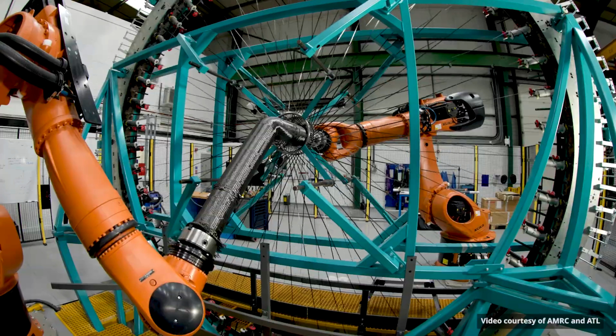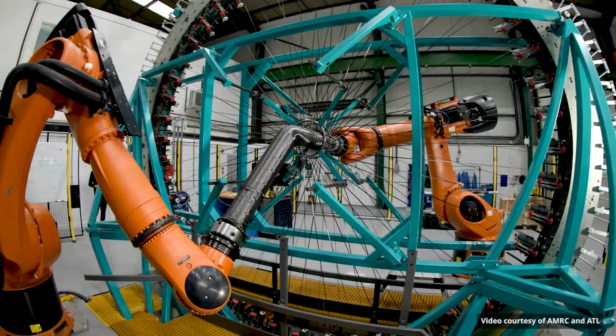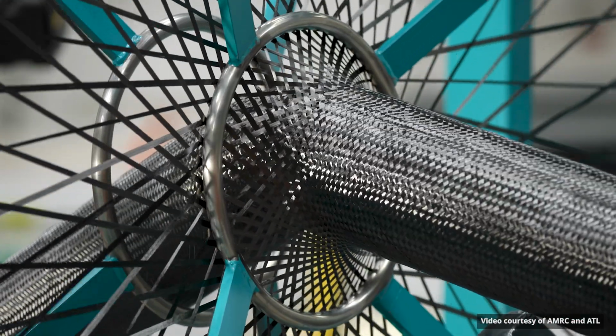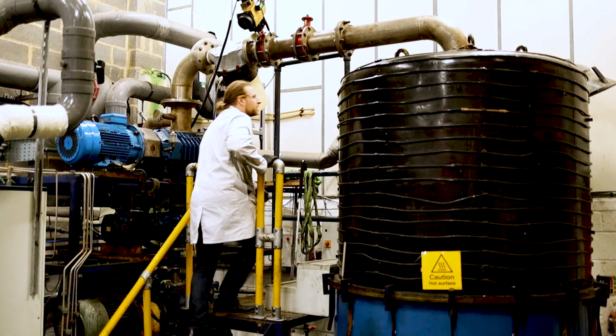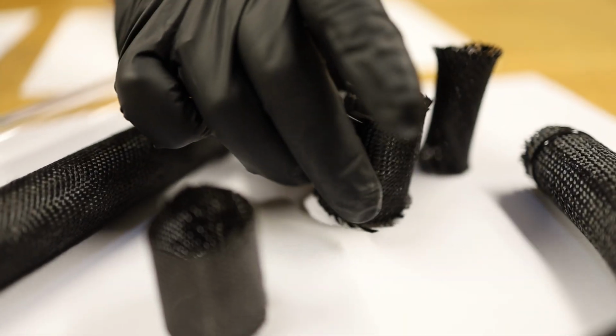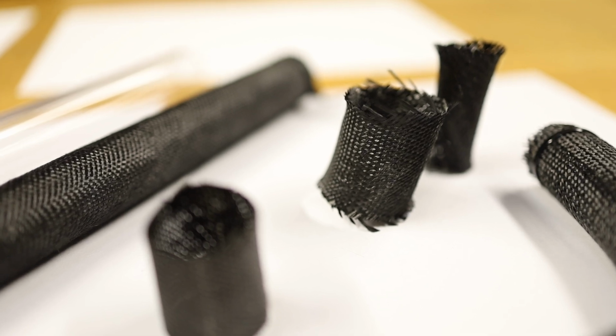We have gone down a different route with braiding of silicon carbide fiber to produce solid preforms that we can then infiltrate and densify with isothermal CVI to produce silicon carbide CMC tubes and elbows. We have then taken these structures and joined them with further isothermal CVI processing, and these are going to be tested at the university, at the Politecnico di Torino,